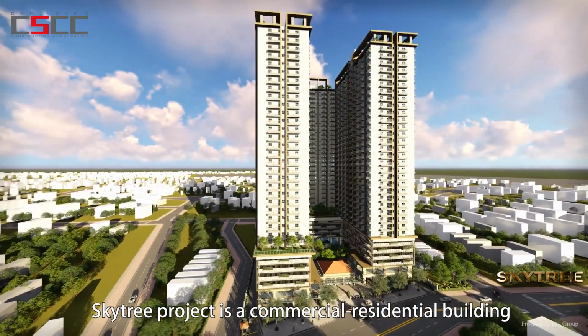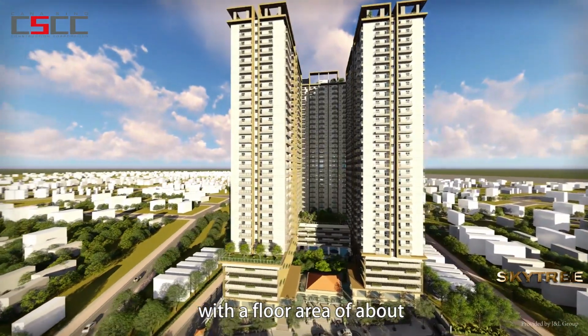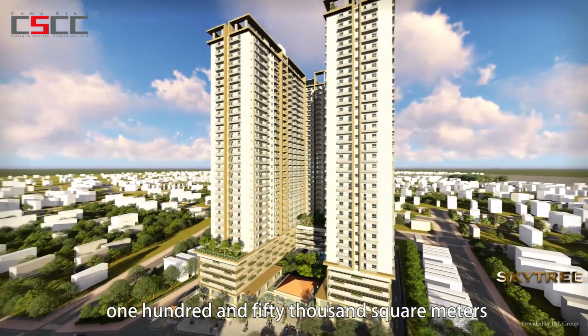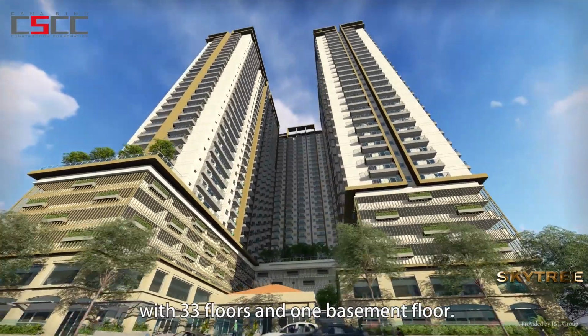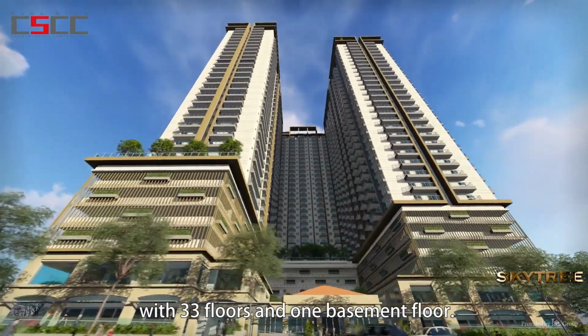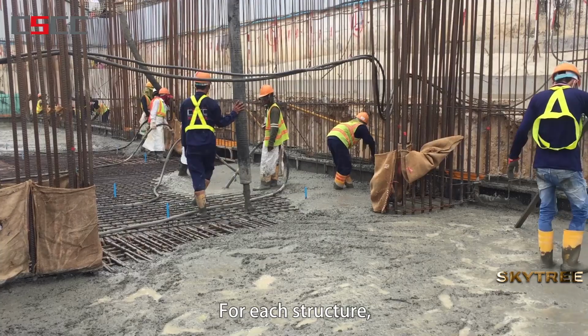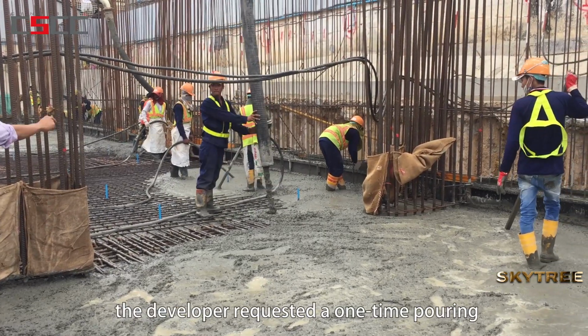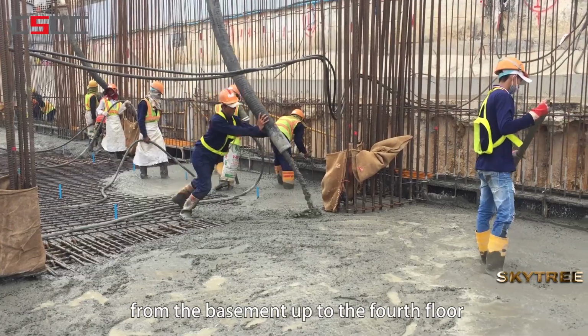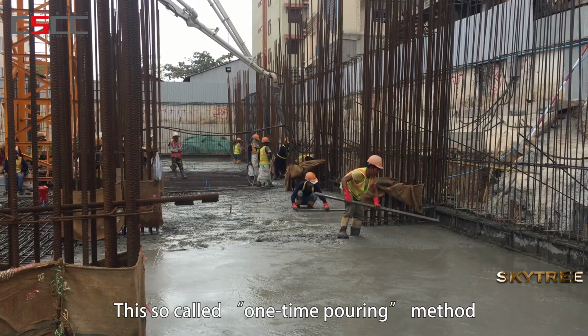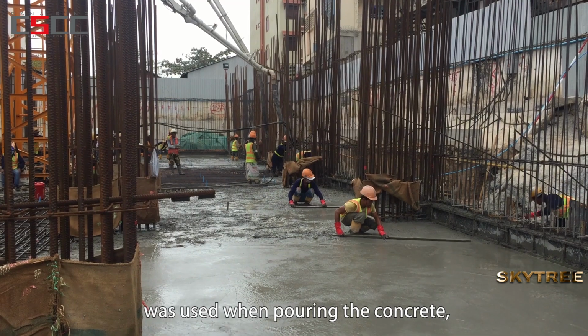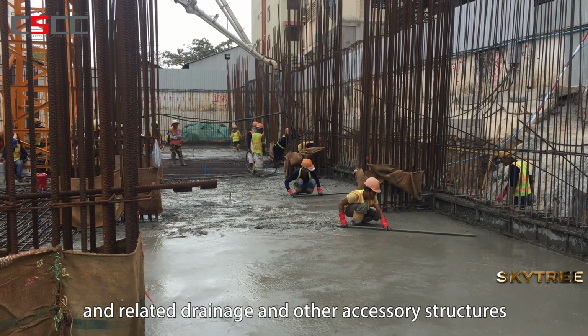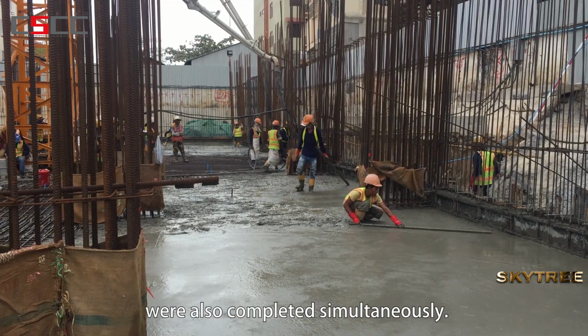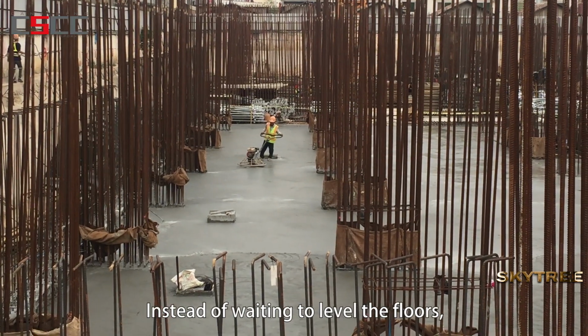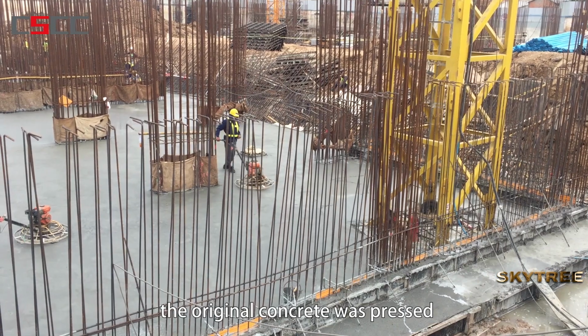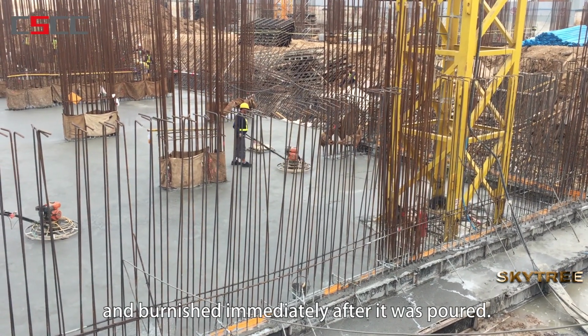Skytree project is a commercial residential building with a floor area of about 150,000 square meters, including three buildings with 33 floors and one basement floor. For each structure, the developer requested a one-time pouring from the basement up to the fourth floor. This so-called one-time pouring method was used when pouring the concrete, and related drainage and other accessory structures were also completed simultaneously. Instead of waiting to level the floors, the original concrete was pressed and burnished immediately after it was poured.